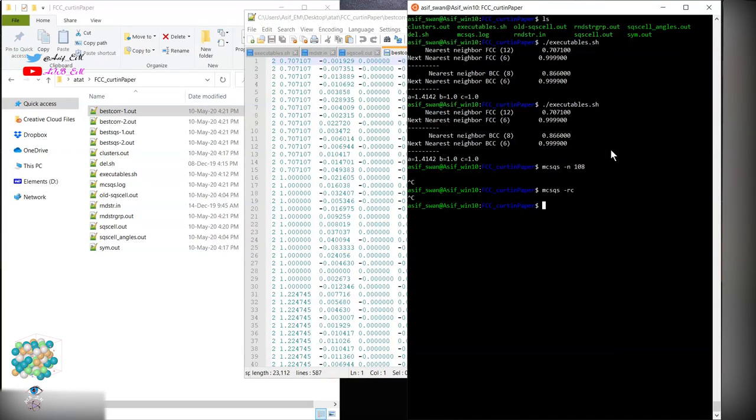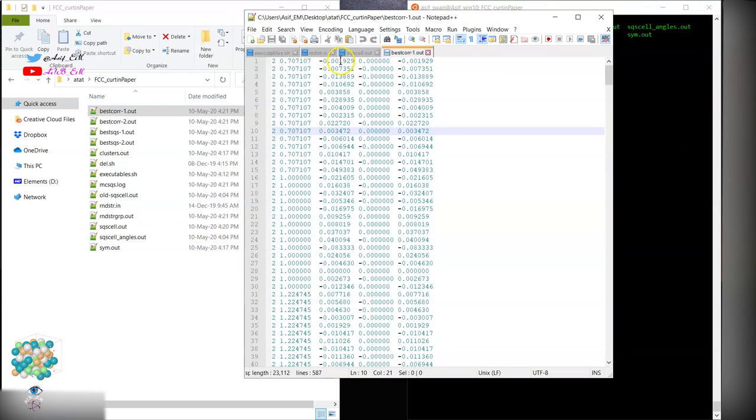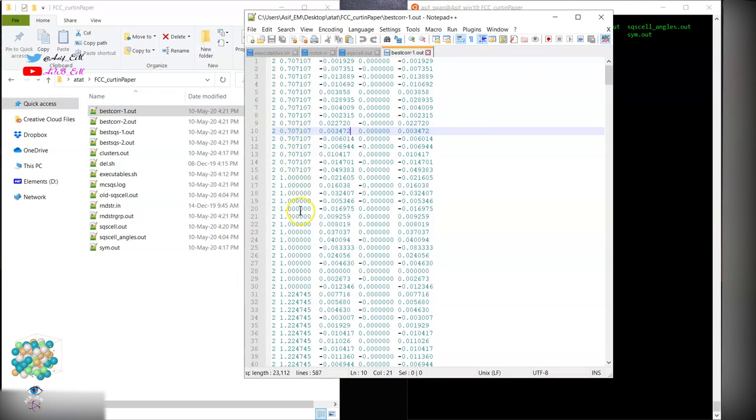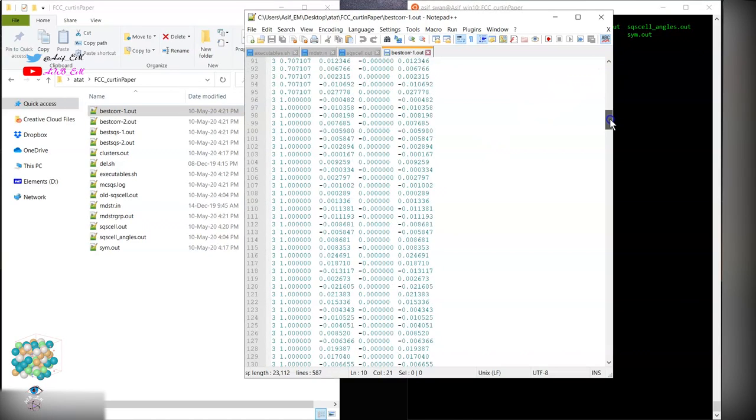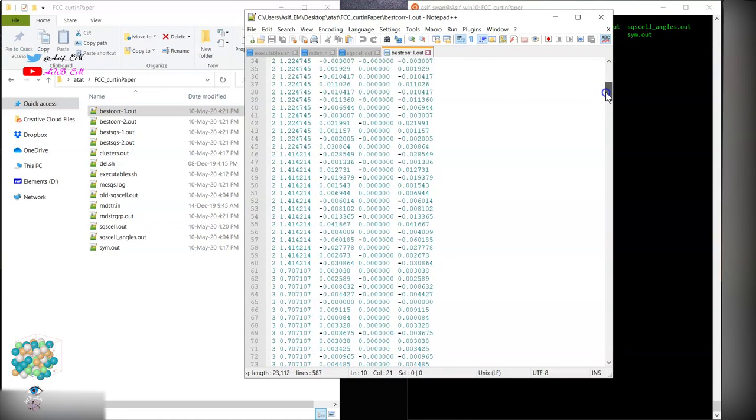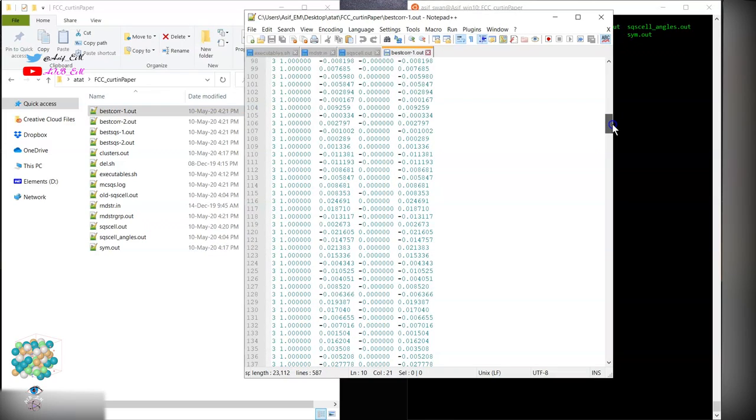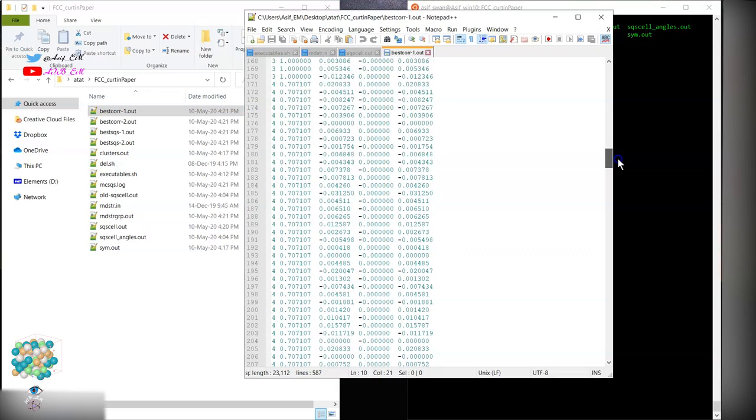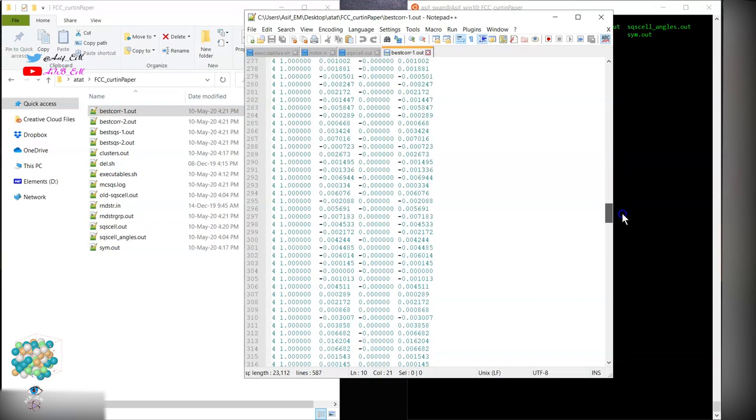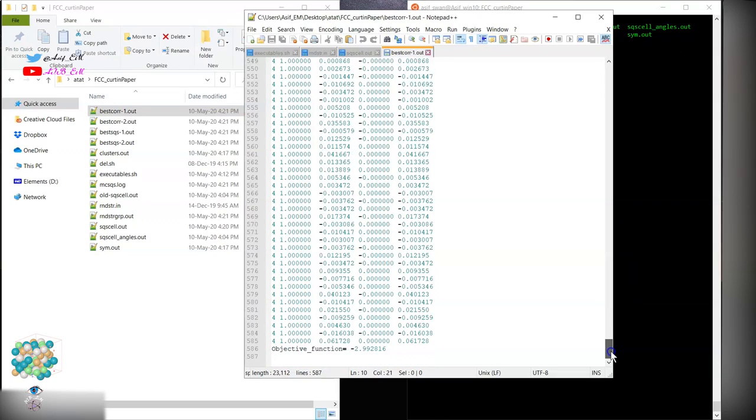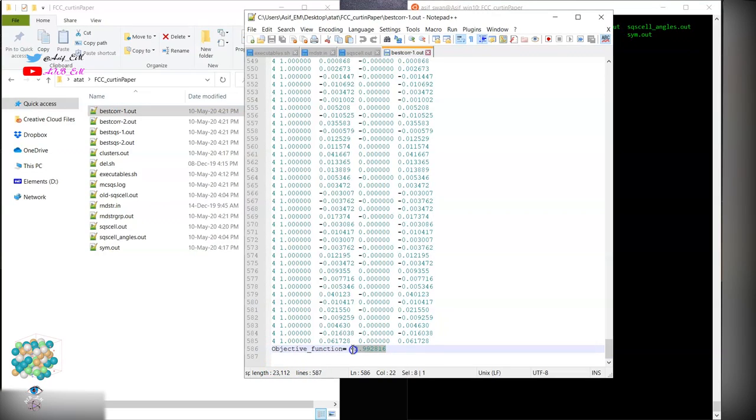For quality purposes, we need to run for many days or months to get the quality results, but it depends on the problem. So the third column over here stands for the correlation function, and fourth one stands for the perfect random alloy, which by definition of covariance is zero. And the fifth column over here is the difference between third and fourth. So for 2, the nearest distance one, how many pairs? Now for 3, triplets, it includes two shells, nearest shells. For quadruplets, we have two again. It shows that FCC is a densely packed system.